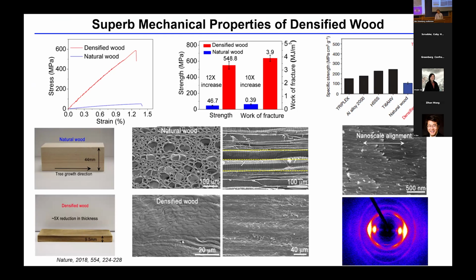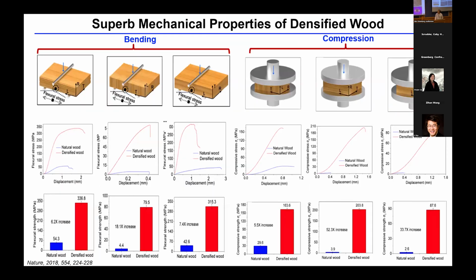Try to get them close in contact so that you can maximize the performance of the fibers themselves, which is all the way up to 7 gigapascals. Our density right now is about 1.3 or 1.35, but the density of the fibers itself is up to 1.5, right? So you see there's a big gap there. That's why I predict, I was trying to work on this, that eventually we should be able to get to 2 gigapascals in a piece of bulk wood.